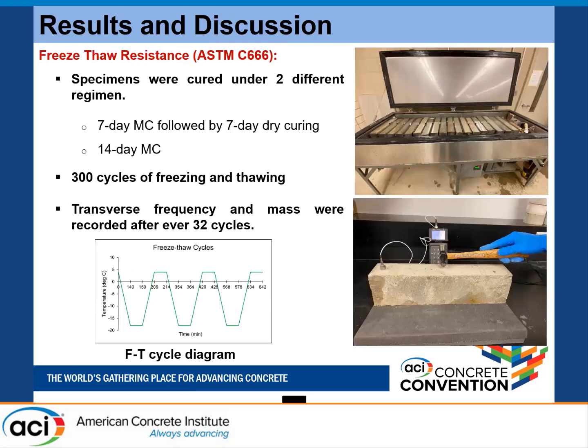And then we did some freeze-thaw testing. Below are the freeze-thaw cycles that we followed. But in freeze-thaw, we used slightly different curing regimes. The standard ASTM C666 method A suggests 14-day moist curing and then 1-day conditioning before putting the samples into the freeze-thaw cabinet, and that we followed. And then we tried to simulate practical conditions, with only 7-day moist curing followed by 7-day dry curing, because no one in the field will cure specimens for 14 days, such a long time. It is practically not possible. Therefore, to simulate practical conditions, we did a brief 7-day moist curing and then just left it in air to see the freeze-thaw resistance of these UHPC specimens.